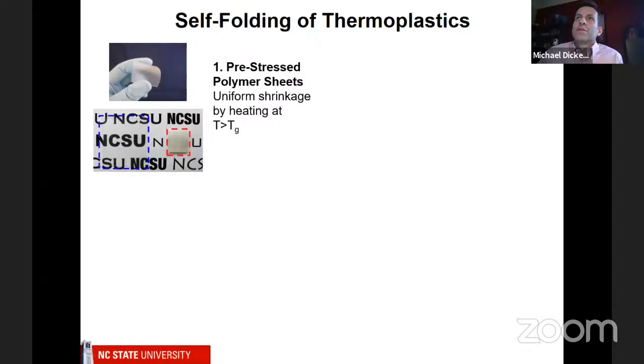And the basic idea here is very, very simple. So we have these polymers, which we actually buy. They're polymer sheets, and they're pre-stressed. This is a key idea. Pre-stressed. So that means that when they were manufactured, they were stretched. And if you take these sheets and put them into an oven, they will go from this initial shape, this blue square, and they will shrink about 50% in the Y direction and 50% in the X direction. And as you can see, they get smaller, but they also get thicker and a little bit rough, and less transparent.